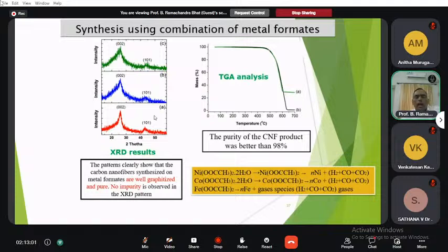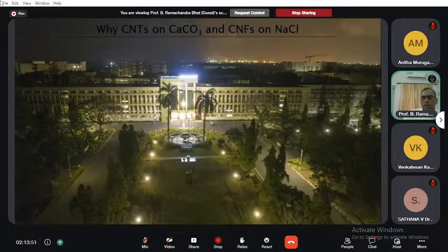Now, the catalyst what we have taken: the advantage of this catalyst is that they are metal formates, either acetates or oxalates. The advantage here is that it directly gives nanoparticles. You can see the reactions here: nickel oxalate, or nickel cobalt or iron oxalate, where on heating the nickel, iron or cobalt nanoparticles are obtained, and the other gaseous species that are obtained easily escape. No impurities will remain. So this can be achieved at a lower temperature also. That's why we have taken the metal formates, and this is the night view of our institute.